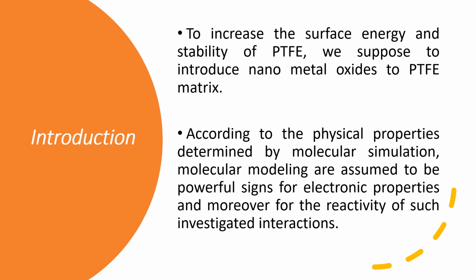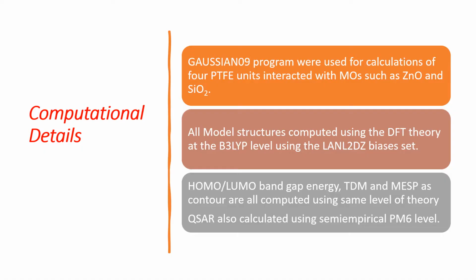According to the physical properties determined by molecular simulation, molecular modeling is assumed to be a powerful sign for electronic properties and, moreover, for the reactivity of such investigated interaction. For our computational details, we used the Gaussian program to calculate the interaction between polytetrafluoroethylene with metal oxides such as zinc oxide and silicon dioxide. All model structures were computed using DFT theory at the B3LYP level using the LANL2DZ basis set. HOMO-LUMO band gap energy, total dipole moment, and molecular electrostatic potential as contour were all computed using the same level of theory. Also, quantitative structure activity relationship was calculated using the semi-empirical PM6 level.